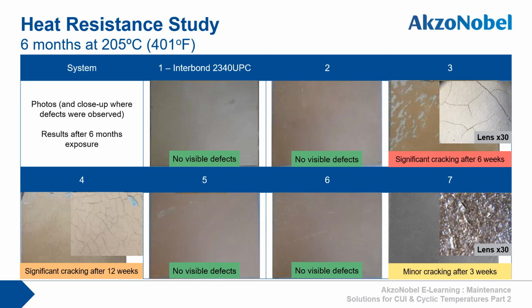After 6 months exposure to 205 degrees Celsius, we see differences in performance. One coating showed significant cracking after just 6 weeks, another significant cracking after 12 weeks, and one some minor cracking after 3 weeks. 2340 UPC and 3 other coatings performed excellently.